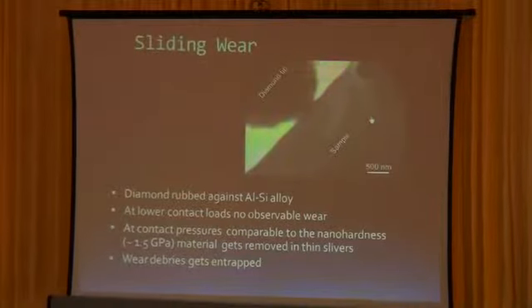So we bring the tip close to the aluminum and bring it in contact. You can see the contours are happening. That is because the sample is bending with respect to the optical plane of the TEM. As we start moving, the bending is changing. You can see the fringes are changing. This is called bend contours. The sample is bending with respect to the incoming electron optical axis. That causes this.